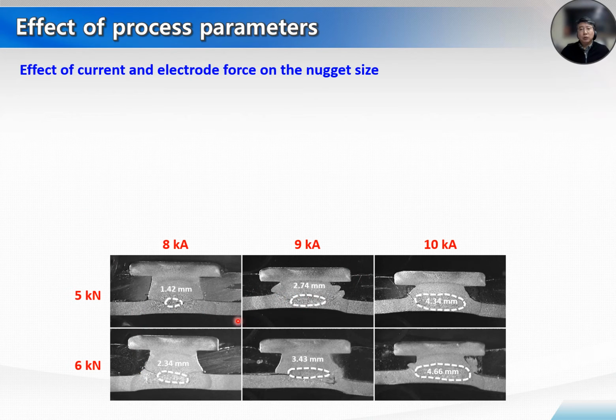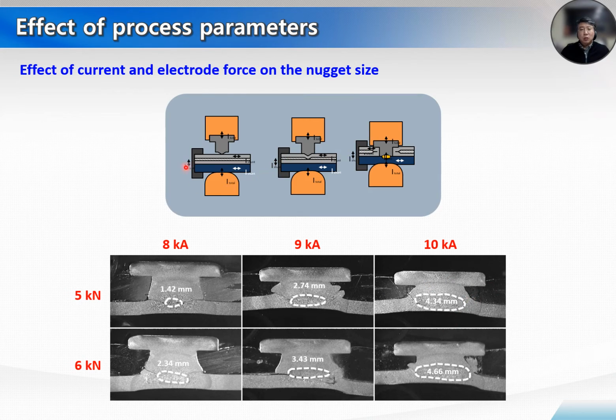nugget diameter increased from 4.34 millimeter to 4.66 millimeter. All of this process has been accomplished by the shunting current clips, and the upslope preheating has been applied, and then main welding was done with the resistance heating between the element and bottom steel sheets. No special defects were observed in the weld area, and as the current increases, degradation of the upper aluminum near the interface was observed. Maybe some melting of aluminum has occurred.